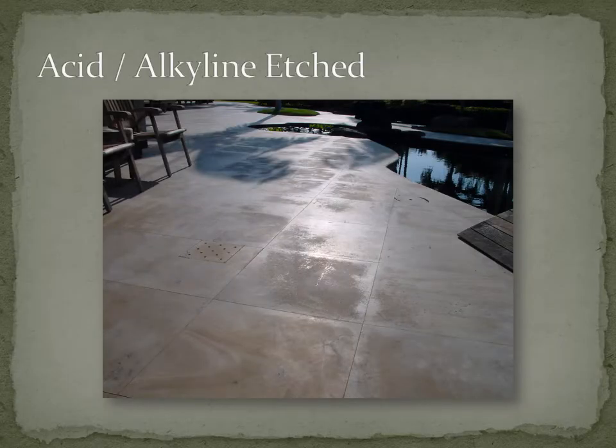This is a limestone floor that's been etched through many years of efflorescence, moisture coming from the mortar bed and leaving salt deposits on the stone, which actually burns it in time. This is a pretty extreme case. You'll see some after photos. We had to diamond sand it and then use honing compounds, but this is caused by just the mineral deposits that were left to sit on there and then get wet again and again and do their burning thing.